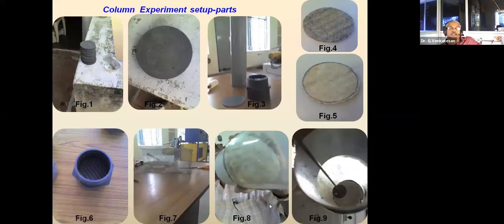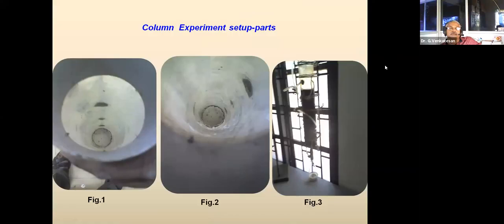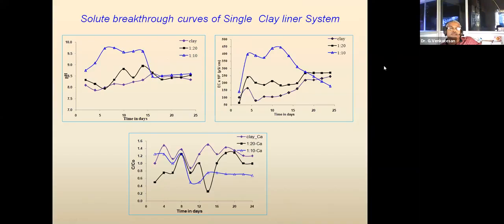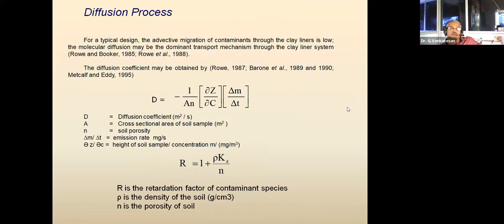So next one, the column experiment setup. We need multiple experiments using an acrylic pipe as well as a PVC pipe. It has a porous stone, with a filter put on the top and bottom surface. There is a GCL on the bottom surface and the top surface. This is the column experiment setup here. So we find the breakthrough curves of the single clay liner system, for clay and 1:10 ratios. Based on that, you find the diffusion coefficient D as well as the retardation factor.